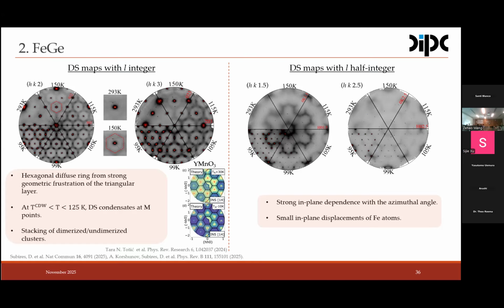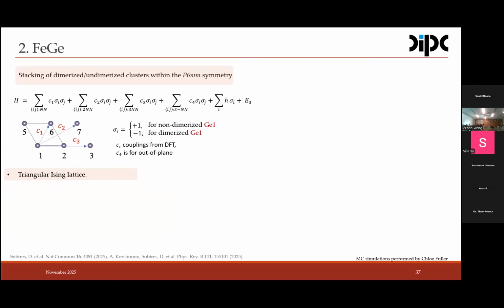So in the same way, the hexagonal diffuse charge scattering we have observed here is a consequence of the geometrical frustration. If we look at the half integer values of L, we do see this hexagonal shape of the diffuse signal, but the hexagon is not closed. And this is a consequence of the in-plane vibration of the germanium and iron atoms in the unit cell. So we can understand this geometrical frustration diffuse signal by considering a stacking of dimerized and undimerized clusters in the P6mm symmetry.